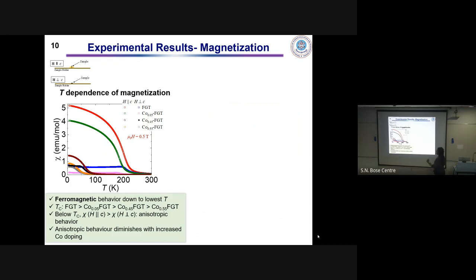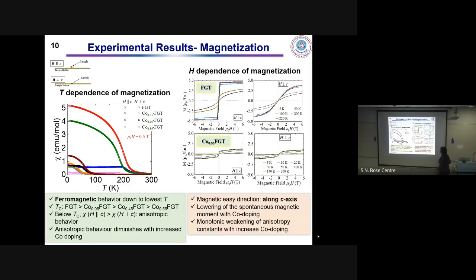As we were increasing the cobalt doping, we could see that this TC was getting diminished consistently with increasing cobalt doping. And not only that, the anisotropy is also getting diminished with increase of cobalt concentration. Further, we have studied the field dependence of magnetization, and here we have seen that in case of FGT, when the magnetic field is applied parallel to the c-axis of the sample, the MH curves saturate at a low magnetic field compared to when the magnetic field is applied perpendicular to the c-axis of the sample. You see the MH curves are still not saturating even at a magnetic field of around 6 Tesla, which confirms that the magnetic easy direction is along the c-axis in case of FGT.